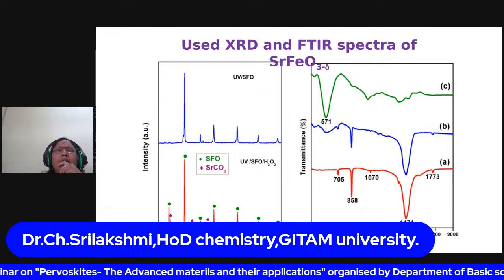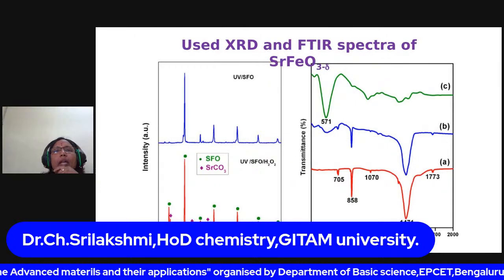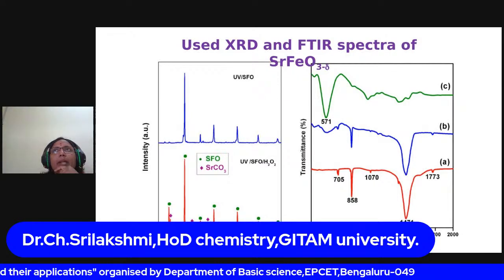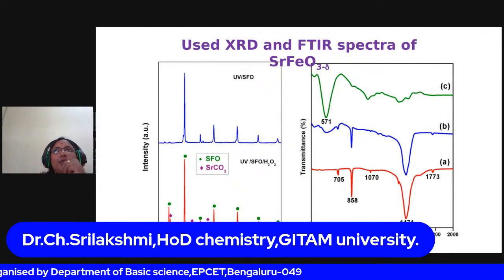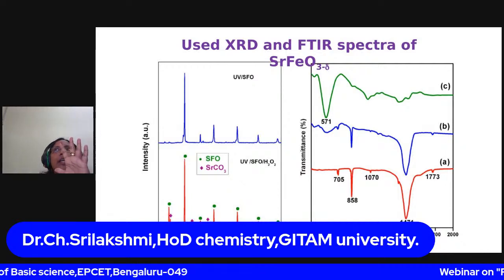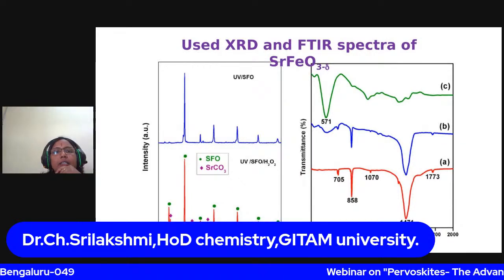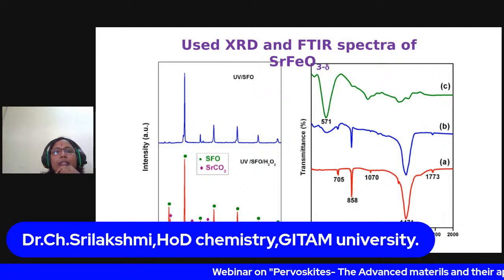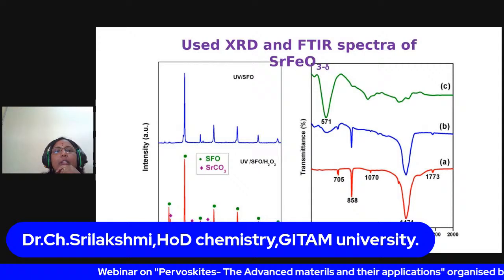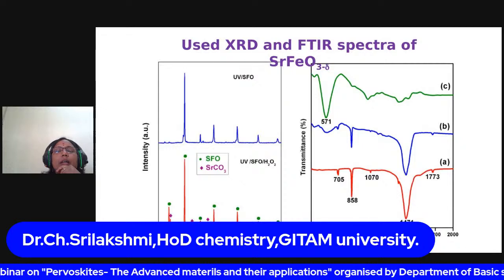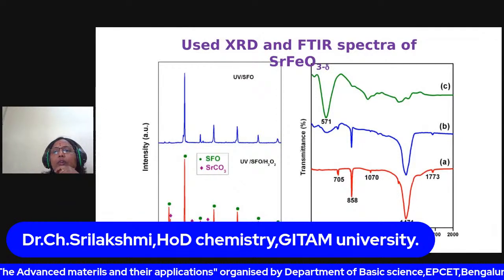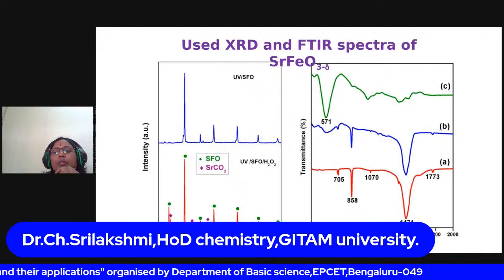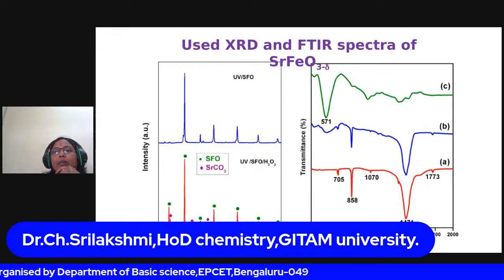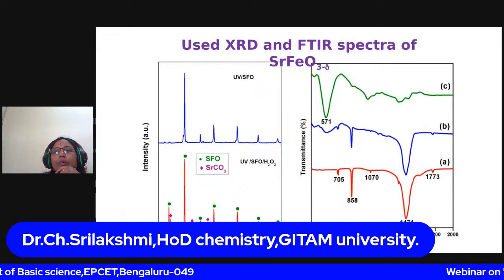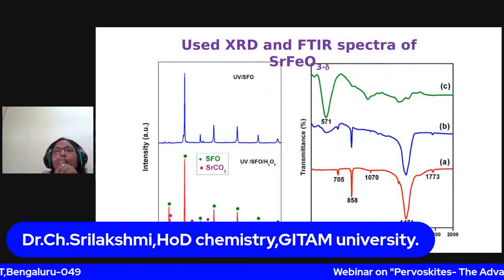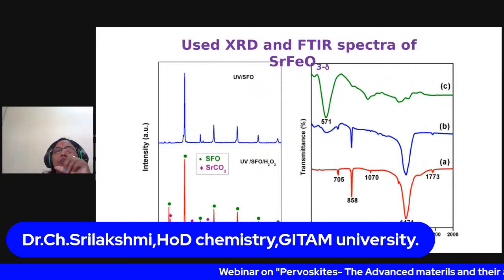So we were thinking, and nothing is happening. So I asked him one day, repeat one of the experiments, and collect the used catalyst and give it to IR and XRD. Then, interestingly, to our surprise, we found these results. So, strontium carbonate is forming in the H2O2-based catalyst. We further confirm this is the standard IR pattern of strontium carbonate, this is the sample IR, and this is the sample with just UV and SFO without H2O2 in the reaction mixture.